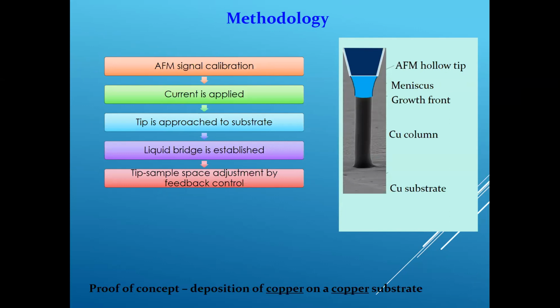surface. Electrical potential or current applied between a small conductive wire inside the pipette and the conductive substrate via the meniscus causes reduction of the reducible material on the surface confined by the meniscus. The dispensing micro nozzle is then moved away from the substrate at a calibrated speed that matches the metal deposition speed in order to keep meniscus formation between the nozzle and the deposited material, allowing continuous fabrication. The majority of the substrate can be kept out of the solution and no masks or sacrificial layers are required.